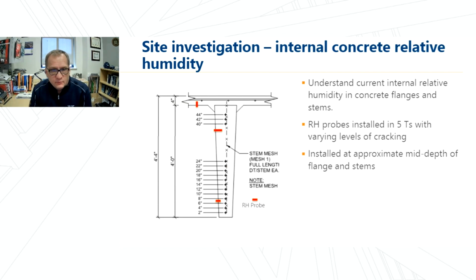And we also did internal relative humidity. Again, we wanted to know what the internal relative humidity of the concrete was to see if it was consistent with the formation of DEF. So we installed 3 internal relative humidity probes on 5 different double T's, with the idea that we're measuring the flange relative humidity and then 2 spots on the stems. And these were installed at the mid depth of each of the concrete elements, because that would have the highest internal relative humidity.